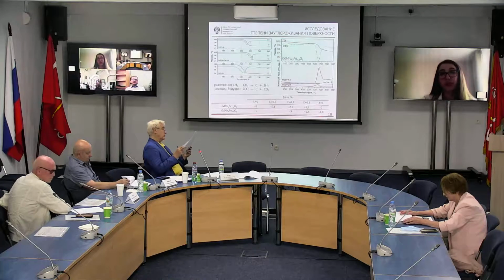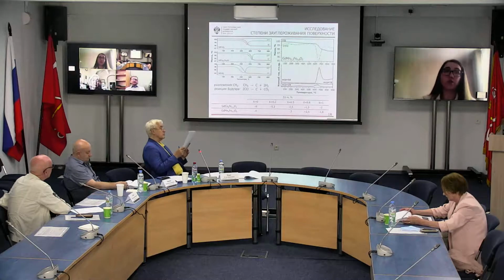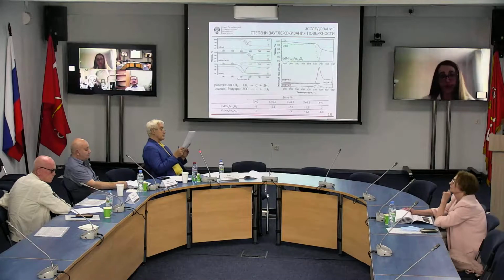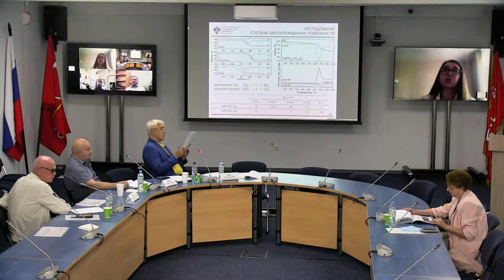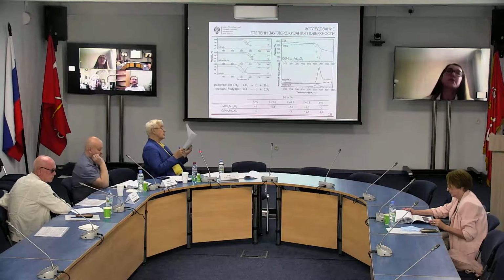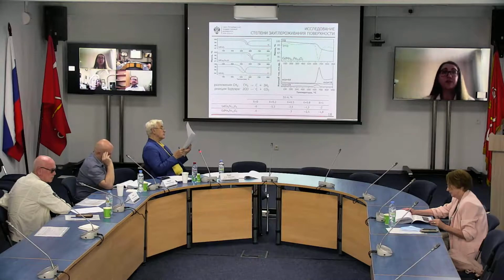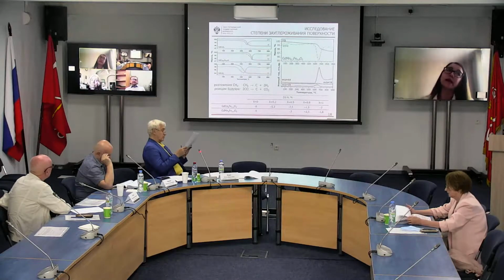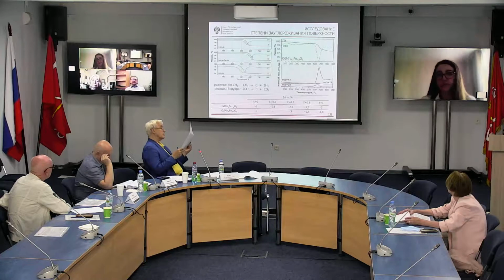According to the results described in the literature, at temperatures below 400 degrees Celsius, we see the incineration of amorphous carbon, and it leads to the formation of synthesis gas. At high temperatures, we observe the incineration of filamentary-like carbon that leads to deactivation of the catalyst. And these values of carbonization of the surface are rather low compared to the ones described in the literature. And this demonstrates the high stability of the developed catalysts. High stability to deactivation of the surface.